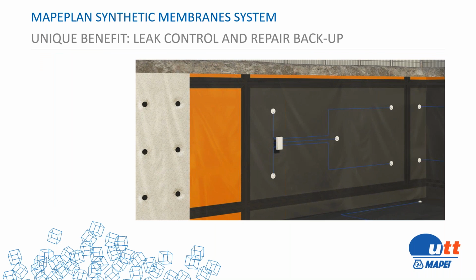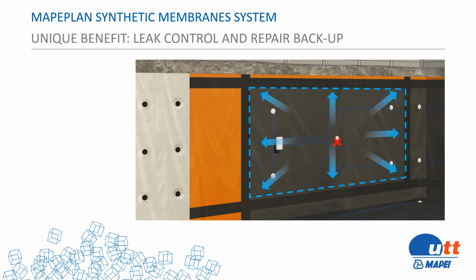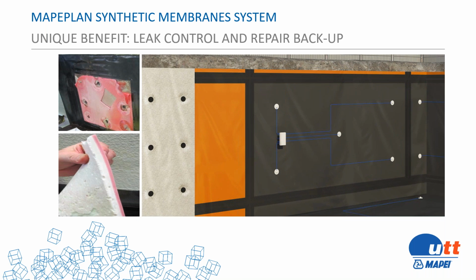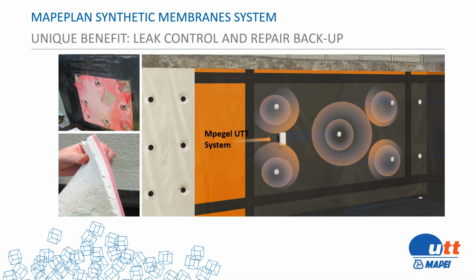As we see now, this compartment has a valve. This valve is connected through the blue hose to a junction box. In case we have any damage, water will start to show from this valve. This is why we call it a testing valve. It's very easy. Once we see water dropping from this blue hose, we connect our injection pump and inject the acrylic gel material through the junction box. This way, we fill the compartment and repair the leakage from the source. This valve gives us very good access to the source of the leakage.